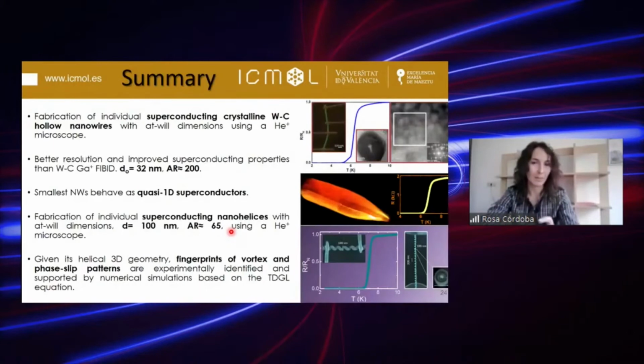And I would like to summarize the main results of my talk. That is the fabrication and characterization of individual superconducting crystalline tungsten carbon hollow nanowires with better resolution and improved superconducting properties, and also the fabrication of individual superconducting nanohelices with at-will dimensions, and that we at least prove that, given its helical three-dimensional geometry, we observe experimentally fingerprints of vortex and phase slip patterns, which are supported by numerical simulations based on the time-dependent Ginzburg-Landau equation.